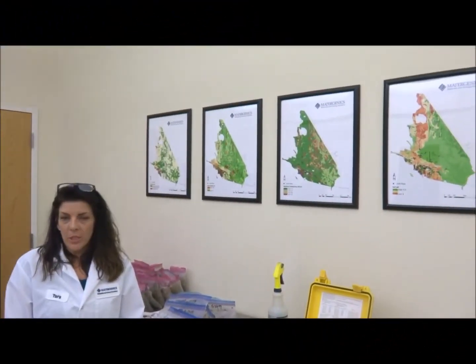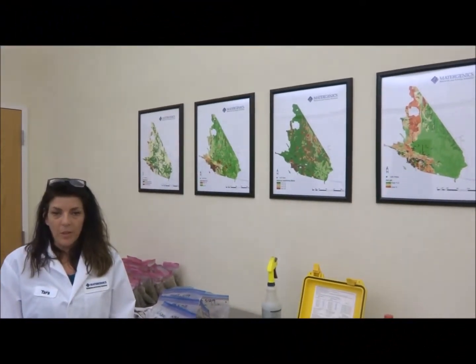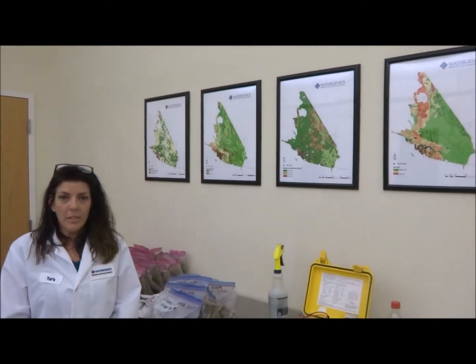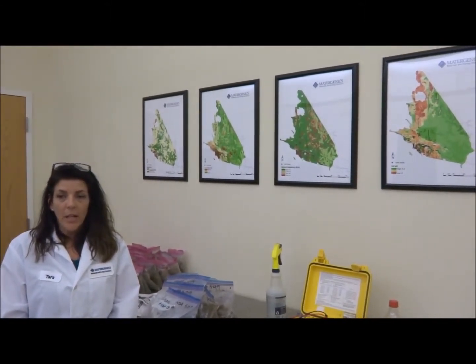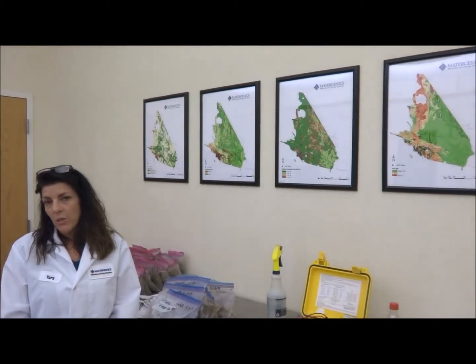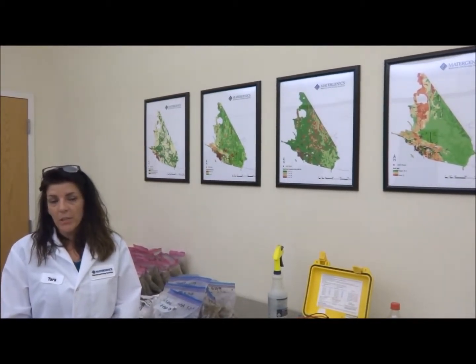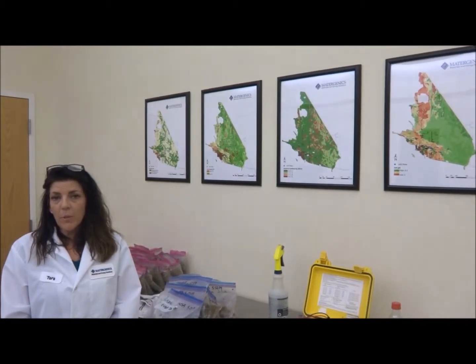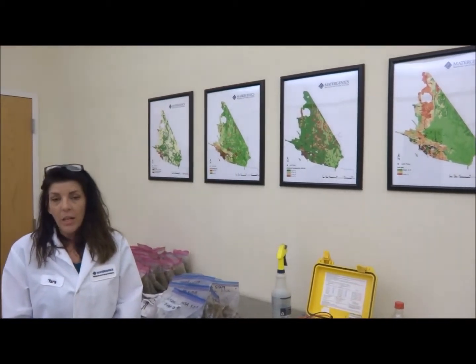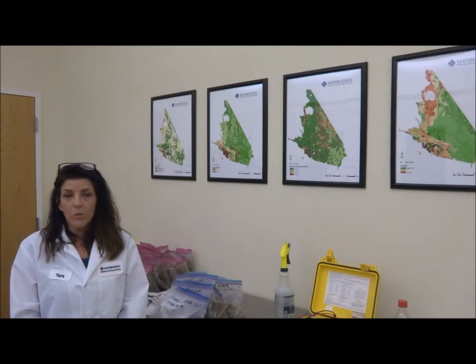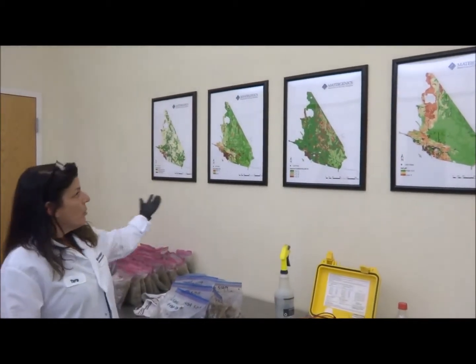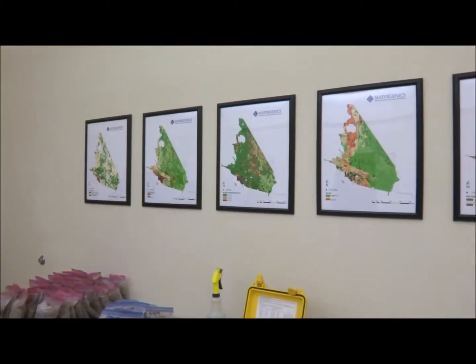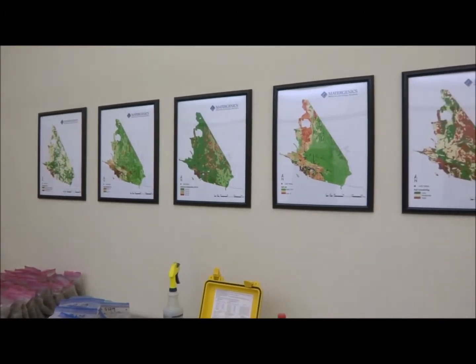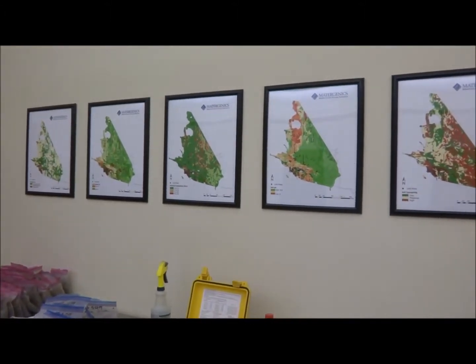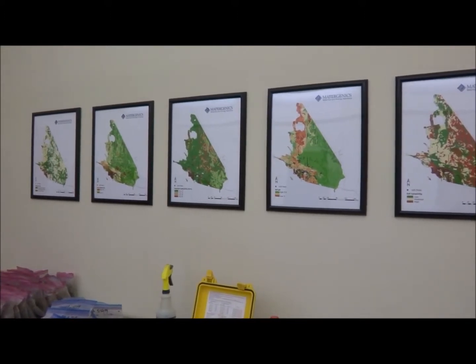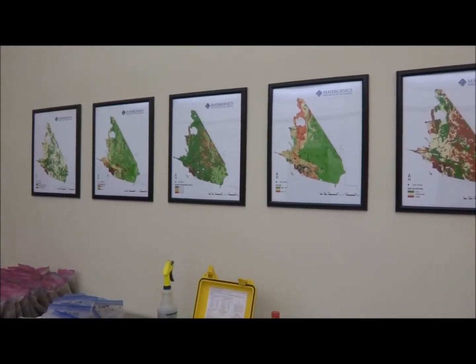Once the soil samples reach the soil lab, we're going to look at the corrosive parameters. We're going to look at resistivity, saturated resistivity, corrosion rate, as well as the chemical properties: chlorides, sulfates, sulfides, pH, and redox potential. When we have this data, we put it together with our field inspection, and we're going to do a corrosion risk assessment. Here you can see we've done a corrosion risk assessment with an area in the United States where we were able to take the parameters that we look at in the soil lab and put them together to identify areas of high risk.